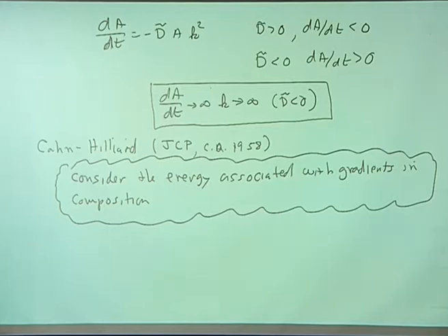And so let me motivate why can gradients in composition change the energy of a system? Okay. Now, this is different from classical thermodynamics, right? Everything we did in the first hour was, I give you a composition, you have the free energy, right? But here what we're going to say is, if I give you a composition, you don't have the free energy until I tell you something about the composition gradient as well.